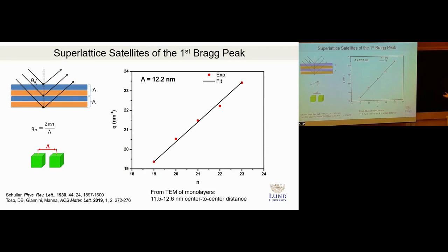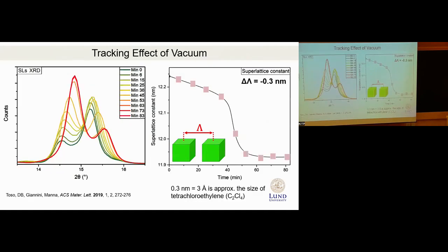So one application of this simple analysis is we can track the effect of vacuum. So once we operate the solvent under ambient pressure, we put superlattices into a diffractometer and we measure the diffraction pattern, and we see that the first Bragg peak has this green colored shape. Then we turn on the vacuum. It's a medium vacuum, so the oil pump, and keep recording diffraction patterns after some period of time. And we see that this pattern evolves.